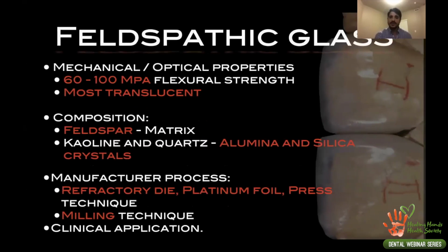The first one is the feldspathic glass. What you will see is that mechanically it has a flexural strength of 60 to 100 megapascal, which is really not a lot. The composition of it has a glass matrix based on feldspar, and we have crystals of alumina and silica. The important aspect here is the manufacturing process. To manufacture a feldspathic porcelain, we have to go through refractory die, platinum foil technique, or you press it.